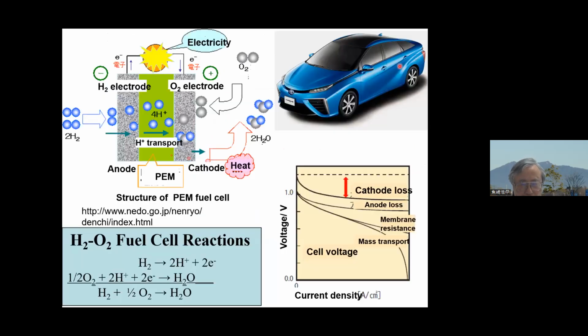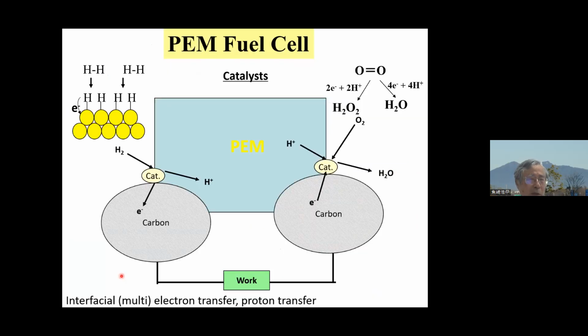Now, as I mentioned, the theoretical potential goes down as soon as you flow the current, which means you run the car. Particularly the loss is due to the cathode. Cathode means oxygen reduction. You can see from here, this is the model of the PEM fuel cell. This is the hydrogen oxidation reaction site, because in this case, the hydrogen molecule can be dissociatively adsorbed on the platinum group surface. It's easy. And once it is adsorbed, it just gives up the electron, and then it becomes proton and electron. Then the electron goes this way, and protons go through the PEM and come to the other side.